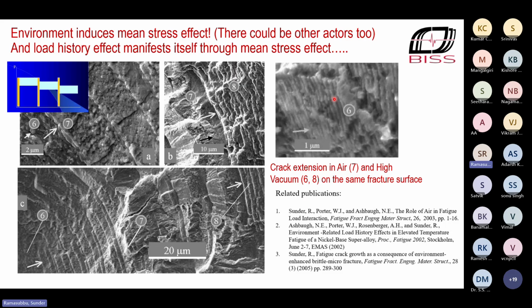It's not going to allow diffusion of active species, right? Because it's like putting a coat of paint and not allowing the environment to attack the surface. And mean stress plays that role by controlling the spacing on the surface of atoms. So surface diffusion of hydrogen released when a metal oxide is formed is probably why we see the mean stress effect in fatigue. So it's one of the reasons.